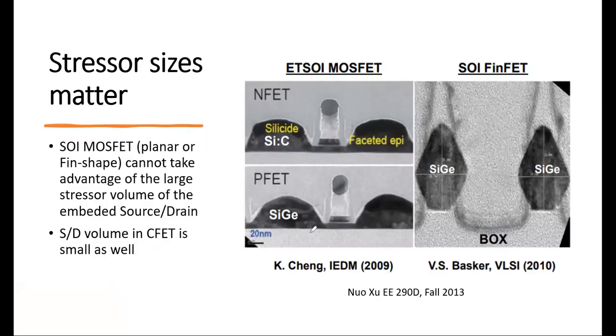stressor. If you look at this, this is the SOI case. SOI has a very thin channel, right? And then the source and drain is smaller because you have a very thin channel in the beginning. So to squeeze the channel, squeezing the strain here is very, very hard. So you get less benefit because source and drain is small. So you had to make it much larger in order to get your benefit back. Okay. And then the SOI FinFET, well, that one you need a big one, right? Just like any FinFET, this is SOI FinFET, but you still eventually had to use a larger volume.